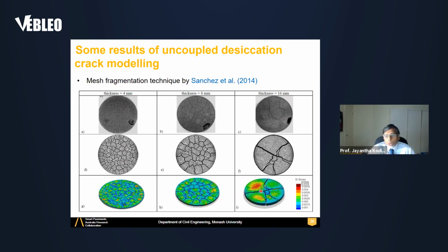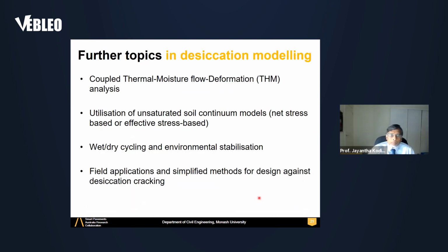As layer thickness goes high, your crack area also goes high, your spacing goes high. So that is in match with the phenomenological observation I mentioned earlier. So you can capture these processes using these techniques.